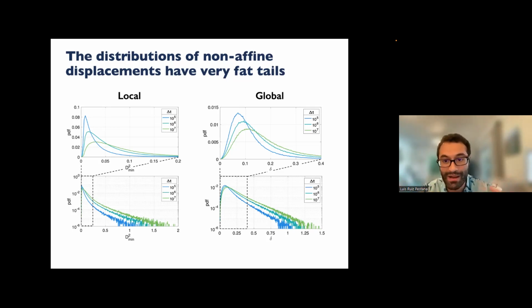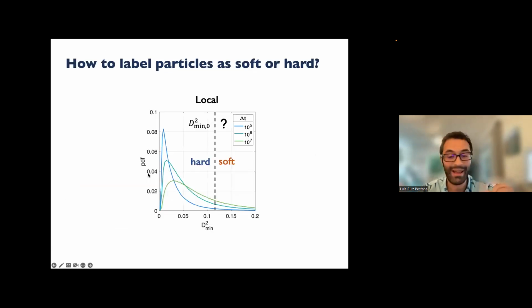This is the basis of why people started thinking about particles in a glass under stress or temperature as having two populations, which we are going to call soft and hard. Hard would be particles that don't rearrange, soft would be particles that rearrange. That is hand-wavy at best, because you should still ask: sure, I buy your argument that the fat tails are the soft particles, but these are still unimodal distributions. So where do you put the limit? What's your threshold to say that if displacements are higher than this number, you have soft particles, and if they are smaller, you have hard particles? This is kind of an arbitrary threshold.